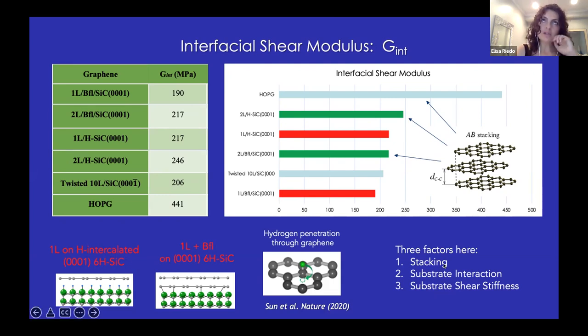So the stacking actually is the one that has the most motivation, because there are DFT studies performed by Annalisa Fasolino that indicate that the C44 elastic constant in graphite, which is essentially the interfacial shear modulus that we are measuring, strongly depends on the stacking. And she demonstrated that, for example, the AB stacking is the most stable stacking in graphite, and is also giving rise to the largest interfacial shear modulus.